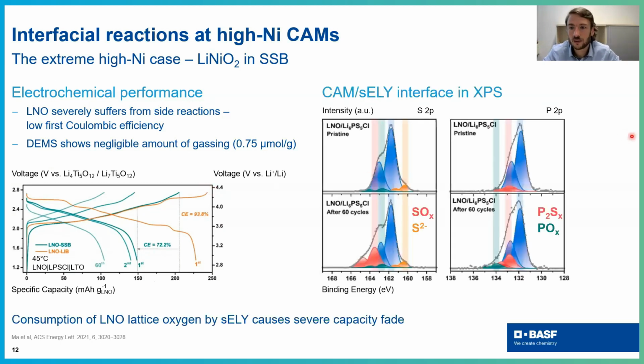And here XPS is surprisingly kind of helpful. So what you see essentially is the arrival of very many additional peaks in the solid electrolyte, or at the interface of solid electrolyte to CAM. They are marked here by red and orange and green. And you observe two types of species here. These are polysulfides and thiophosphates, but also you observe oxygenated species like SOx, SO3, SO4 anions, and POx species.